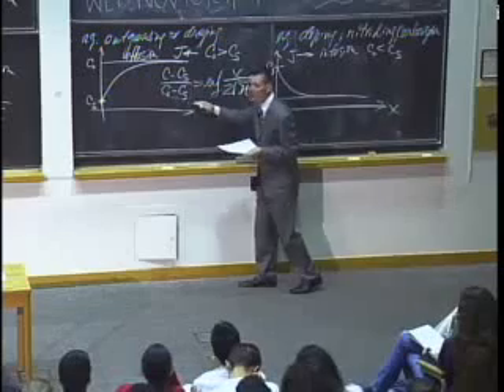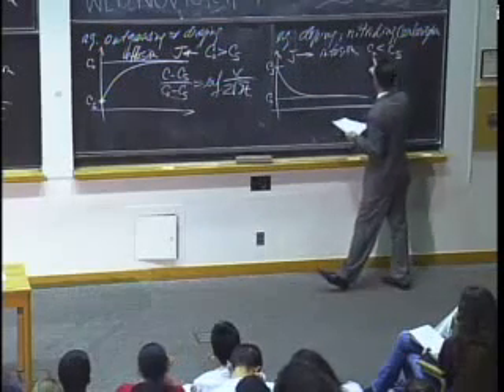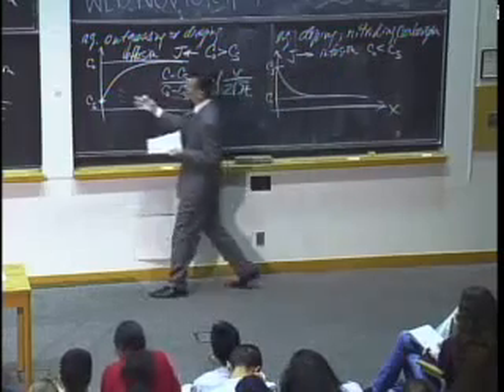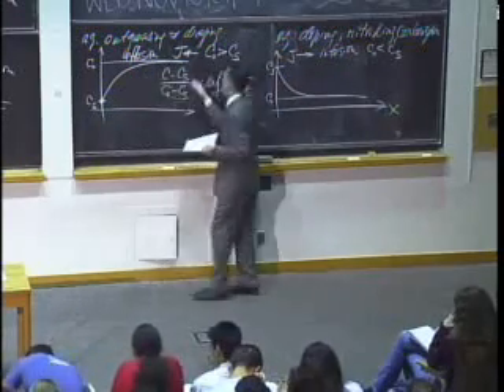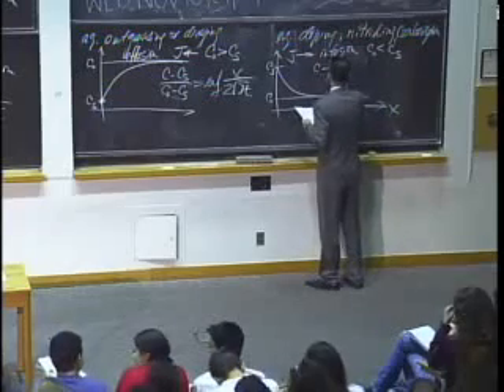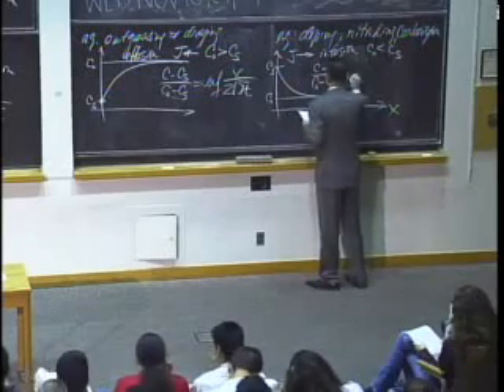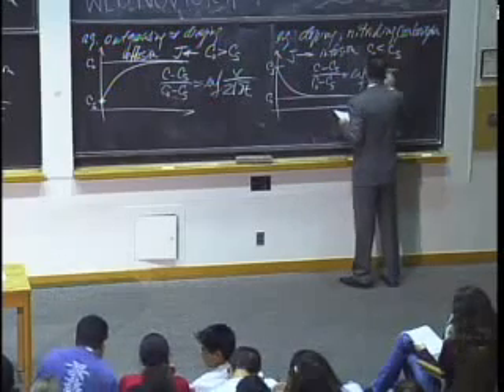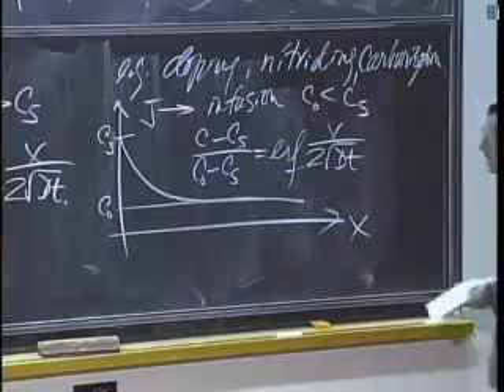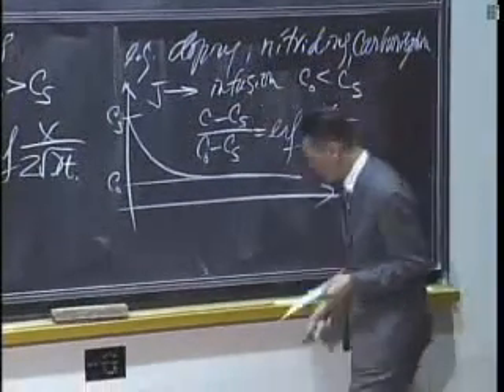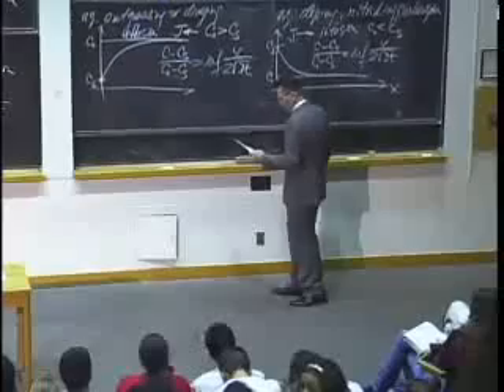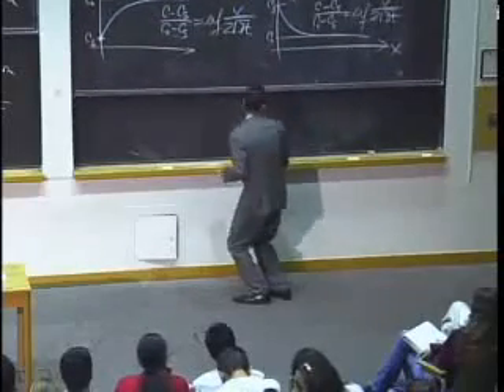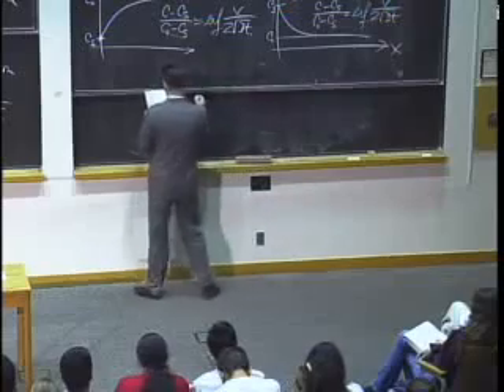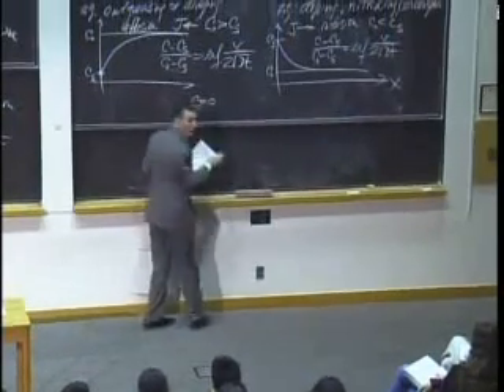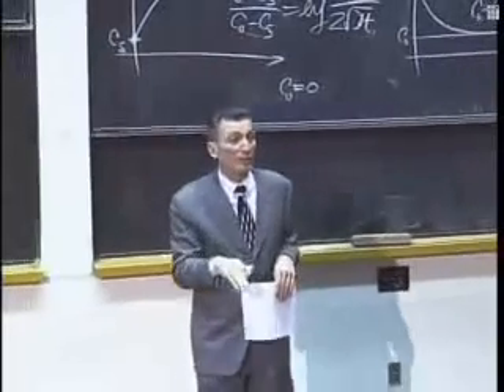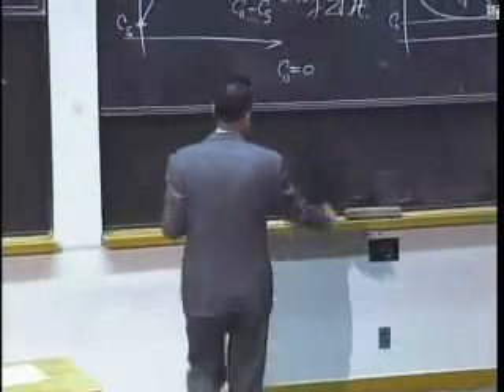And again, this same general solution applies whether the surface concentration is higher or lower than the initial bulk concentration. It comes out in the math here. So again, we write (C minus Cs) over (C naught minus Cs) equals ERF of x over 2 root Dt. And this one comes up very often. This is the way it works in doping of semiconductors, and comes up so often that it's convenient to define another function where in many instances C naught equals 0, right? When we're doping pure silicon, the initial concentration of boron or phosphorus in pure silicon is going to be 0.